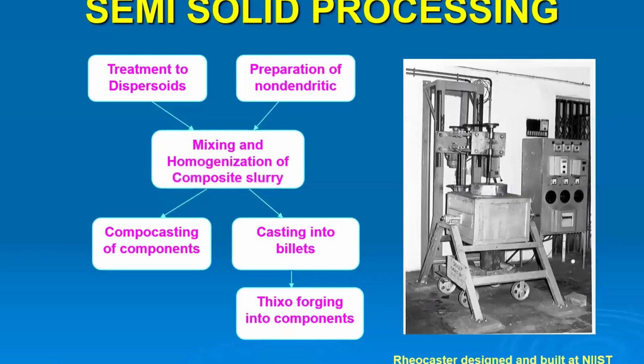And the second technique is semi-solid processing. Semi-solid means we have a semi-solid region. Some alloys melt at high temperature; if you take aluminum, the melting point is 660. If you have alloying additions, because of the colligative properties, there is a depression of the freezing point. If you take a 356 alloy, the melting point is around 615, and the solidus is around 577. So in between 577 and 615, there is a partially melted region which is called semi-solid.